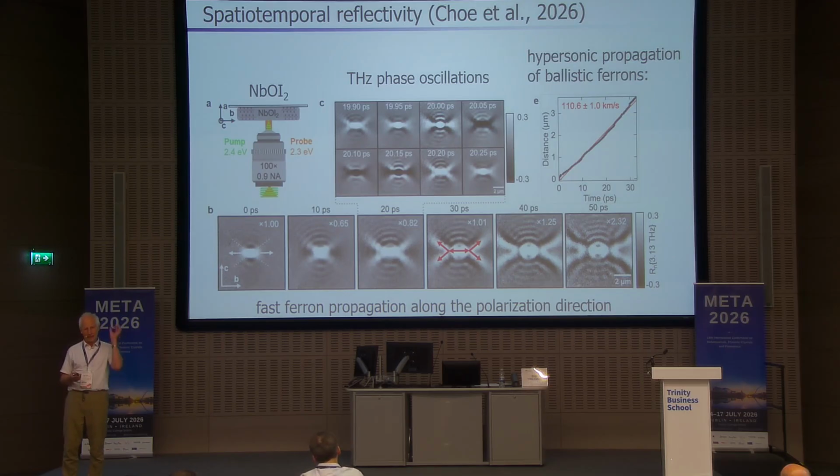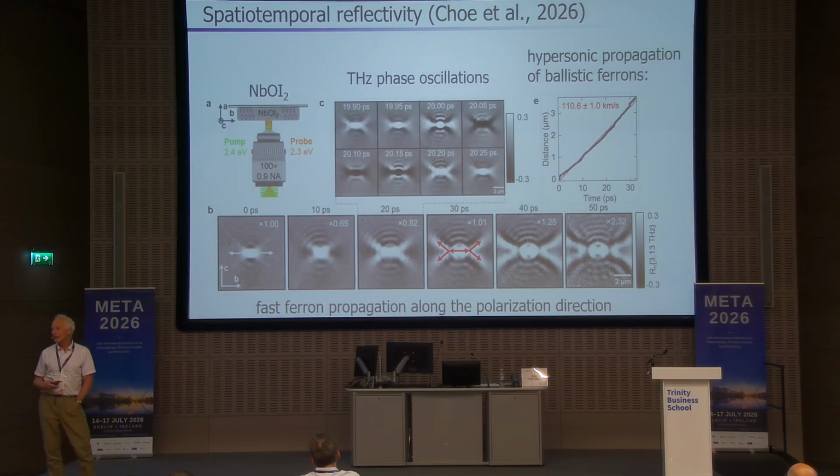Here you see how, as a function of time, the signal expands. So it's like a stone you throw into the water and see that the water waves expand. Only here it's strongly asymmetric and with a little bit strange phase shape. Now, interesting here is the velocity of the wavefront, which is indicated here, which is much faster even than the sound velocity in these materials, and orders of magnitude faster than what you expect for an optical phonon. Okay, so this is quite promising for the future, also for information transfer. Yeah, I should also say that this goes really very far.